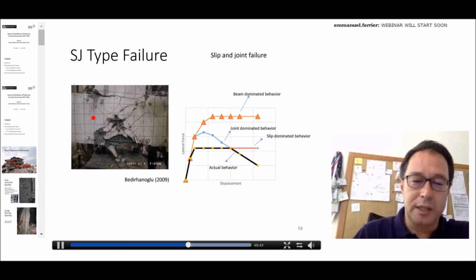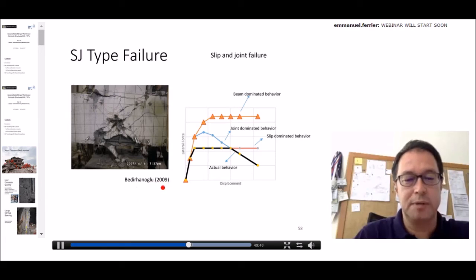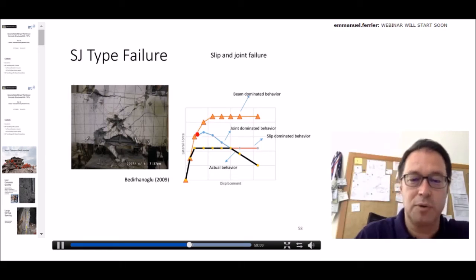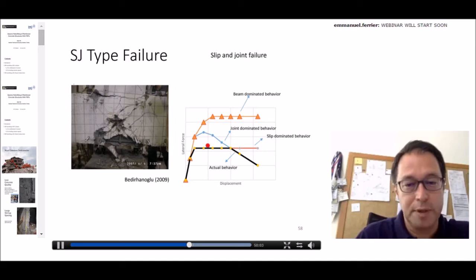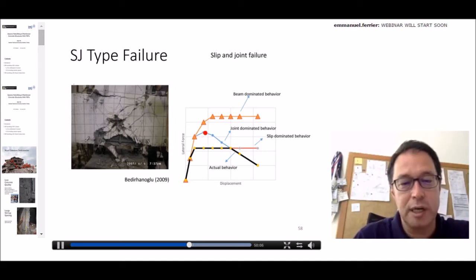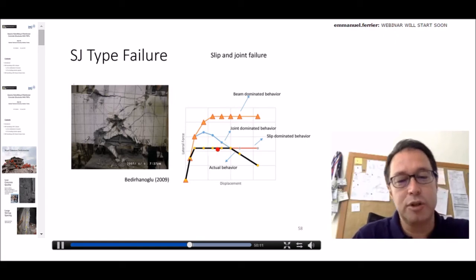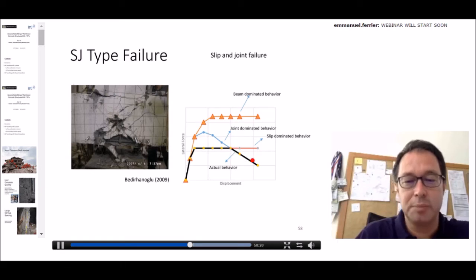In the specimens tested by Bedirhanoglu, my previous PhD student, the behavior was first governed by slip of the longitudinal bars of the beam in the negative moment area, and the slip caused deformations at a much lower strength, never reaching the yield strength of the beam or the shear strength of the joint, which is somehow good because if we reached the shear strength of the joint, then the behavior would be brittle. Nevertheless, we have a kind of pseudo-ductility until a certain displacement, and when we reach the point where the shear strength is reduced to the same level, the shear behavior of the joint governs.